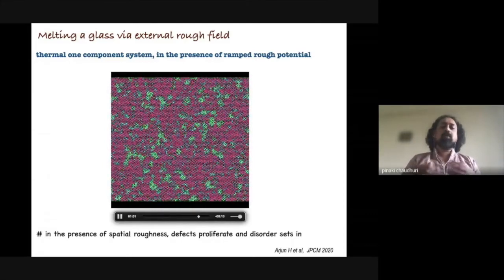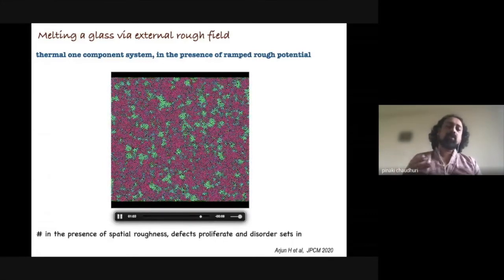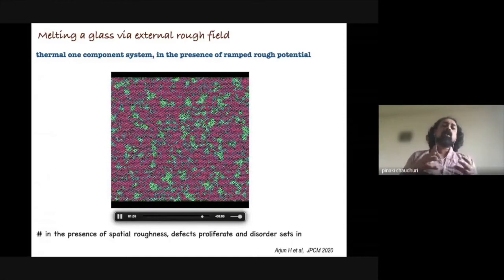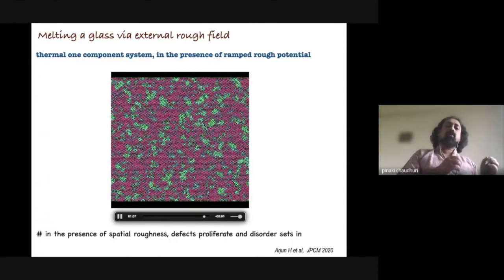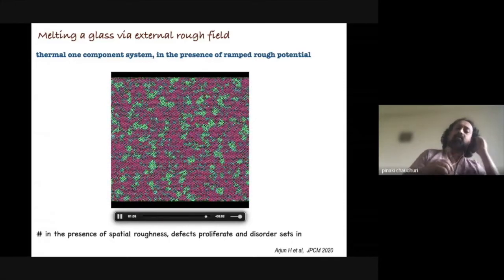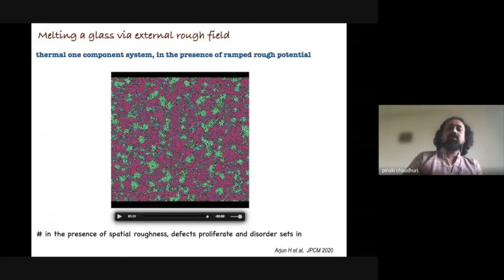So in this way, one can be more quantitative, and this is what we have done. You can then observe how this order goes into a disordered structure as a function of time as you increase the roughness of the external potential.